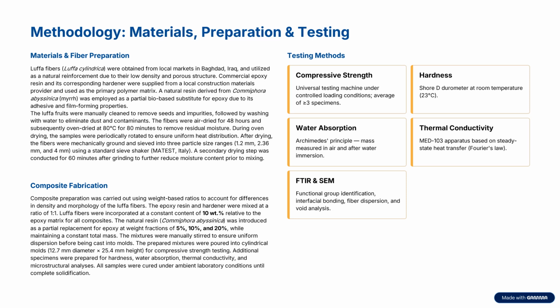After drying, the fibers were mechanically ground and sieved into three particle sizes ranging from 1.2 mm to 4 mm using a standard sieve shaker. A secondary drying step was conducted for 60 minutes after grinding to further reduce moisture content prior to mixing. For that, the composite fabrication was carried out using weight-based ratios to account for differences in density and morphology of Luffa fibers.